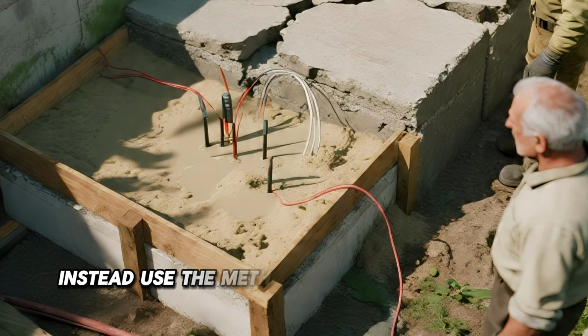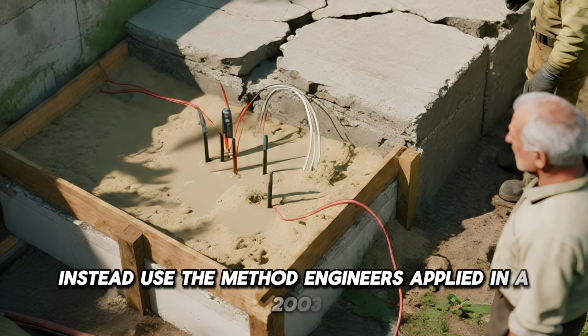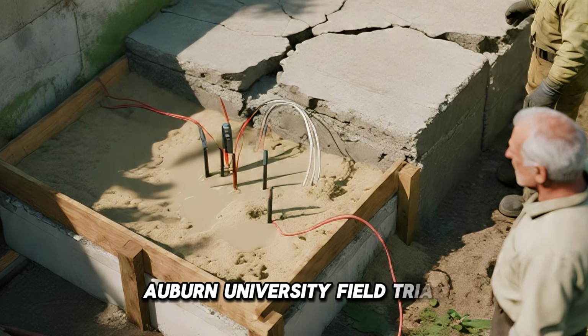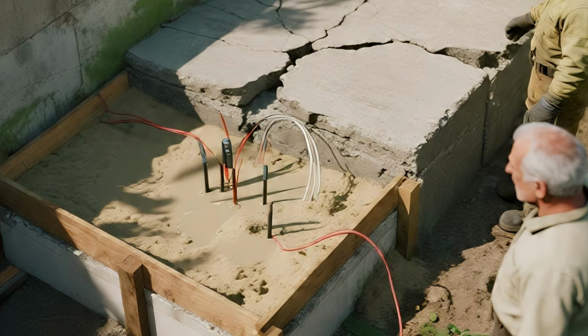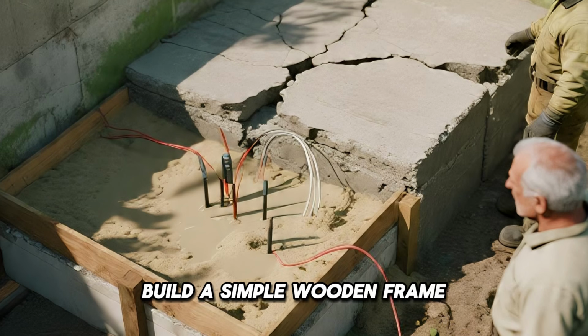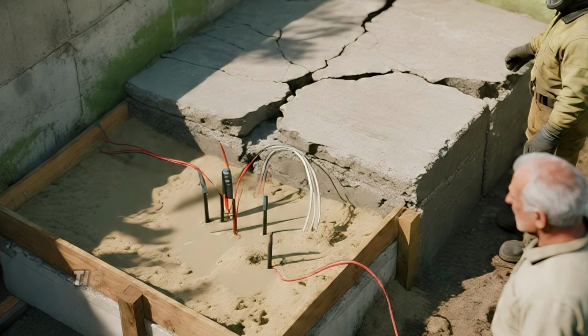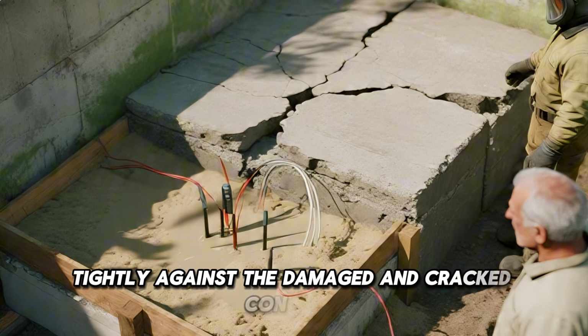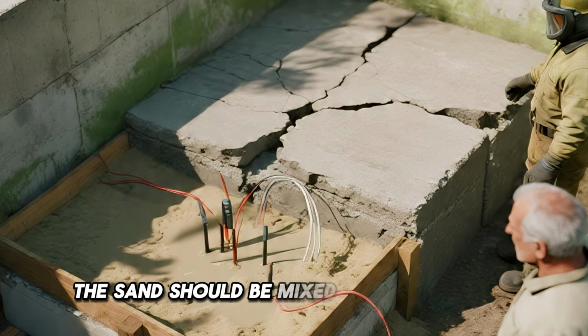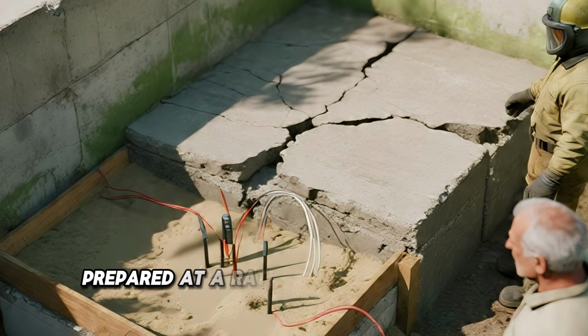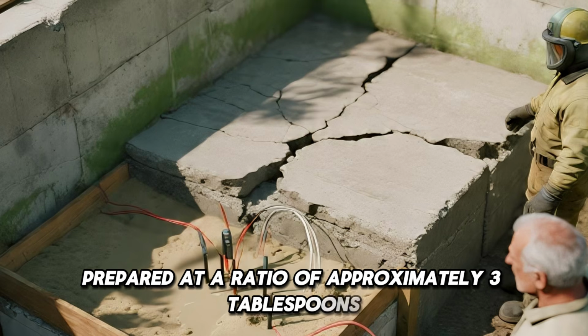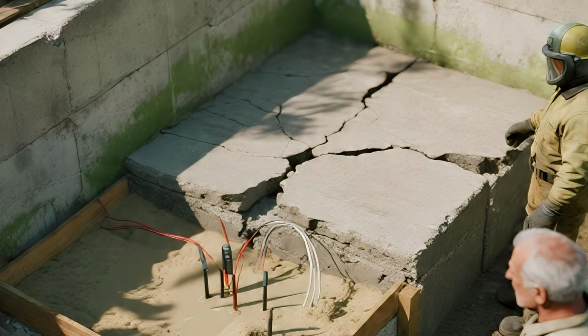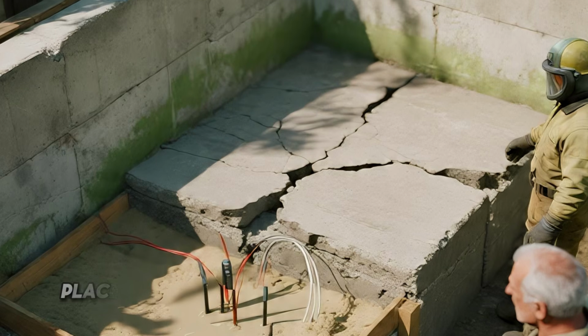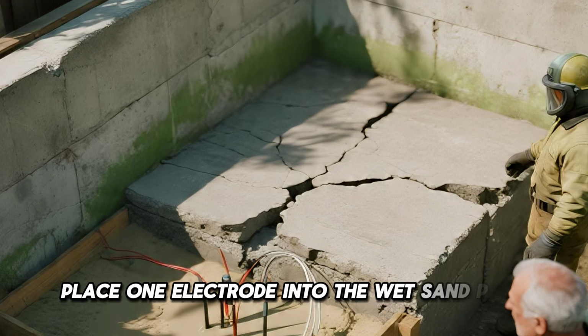Instead, use the method engineers applied in a 2003 Auburn University field trial involving marine structures. Build a simple wooden frame and pack wet silica sand tightly against the damaged and cracked concrete. The sand should be mixed with salt water, prepared at a ratio of approximately 3 tablespoons of non-iodized salt for each gallon of water. Place 1 electrode into the wet sand pack.